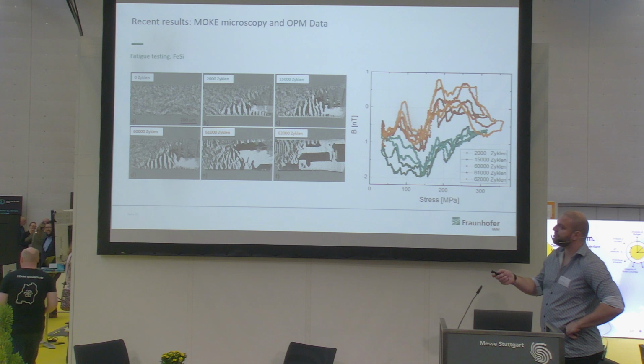So we had one of the tensile samples. We start here at 0 cycles. There's a residual stress layer from polishing on top, which is why we don't see any domains here. Then we go through the cycles up to 62,000 cycles, and we see this pattern evolving. But in this case, it evolves to a certain pattern up to 60,000 cycles, and actually not much is happening.